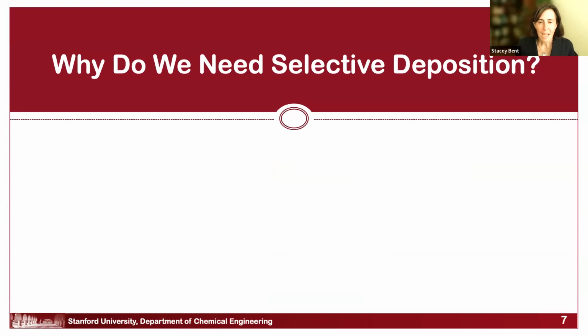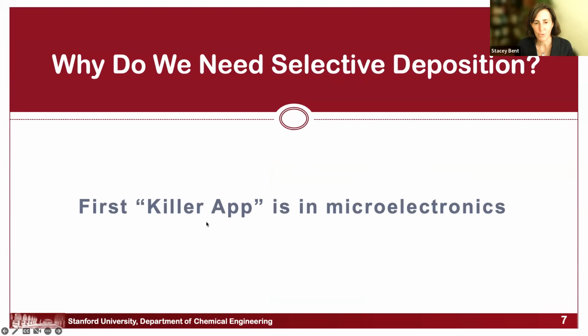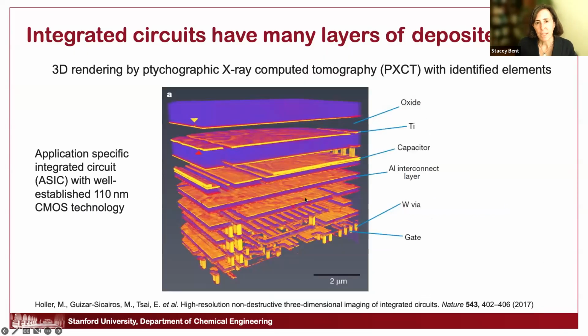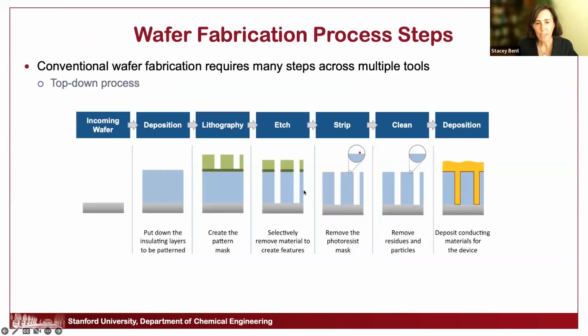I'm going to actually focus on one type of ALD, which is selective deposition. And you may ask, why do we need selective deposition? I think the first killer app of this technique, which people have been looking at for years, is really in microelectronics. And to understand where that comes from, if you think about an integrated circuit, of course, it has so many layers of deposited material, and each of those need to be aligned just right on top of the underlying layers and patterns. And this is where complex fabrication is used. So conventional wafer fabrication requires many, many steps across multiple tools. So for every one of those layers in the structure that I showed, there's deposition followed by lithography and etching and stripping and cleaning and then more deposition. And it's very much a top-down process where material is put down and then removed where required.